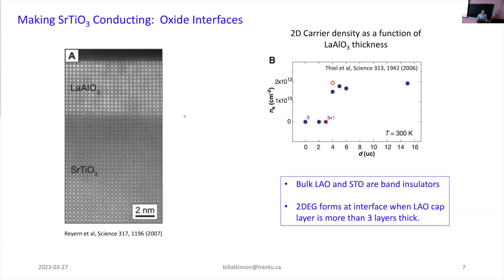But it's not a conductor right away. So the picture on the right here, this is Hall measurements of the electron density as a function of the number of layers of lanthanum aluminate. And when I have two layers of lanthanum aluminate, my free electron density is zero. That's still true when I have three layers of lanthanum aluminate, so it's not a conducting interface, but as soon as I get to four layers of lanthanum aluminate, the interface becomes conducting. So this made a big impression on me when I read it, and I decided to learn more about it.